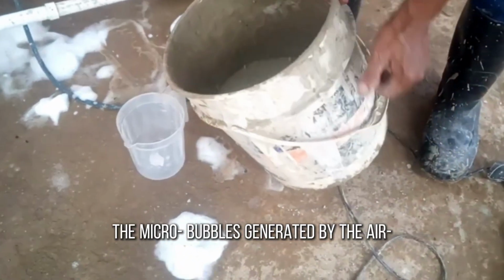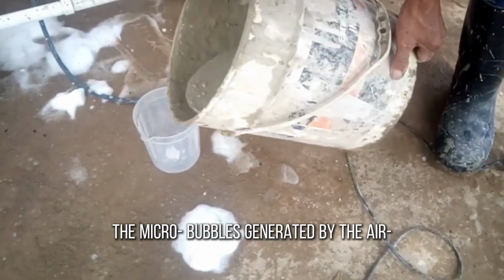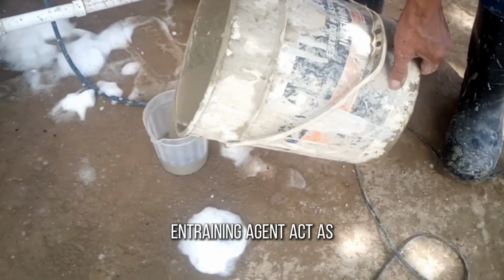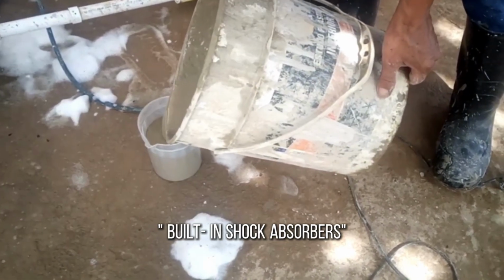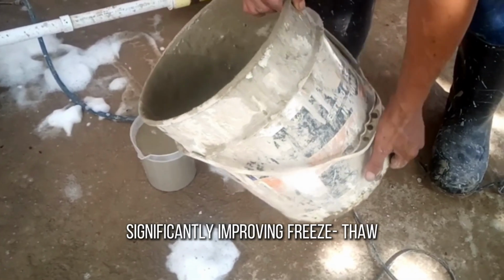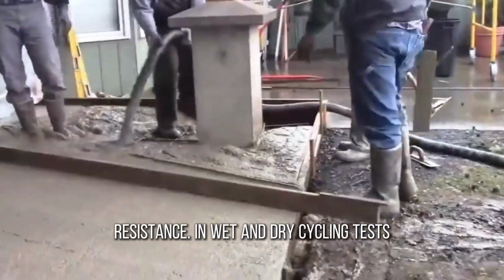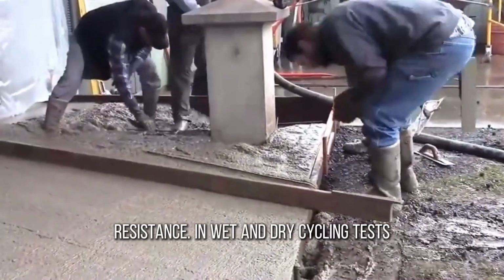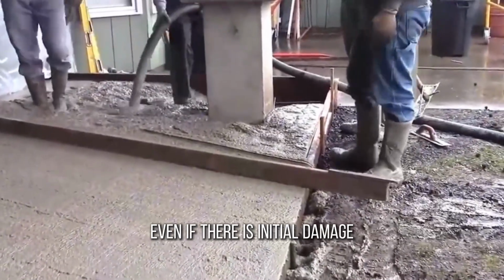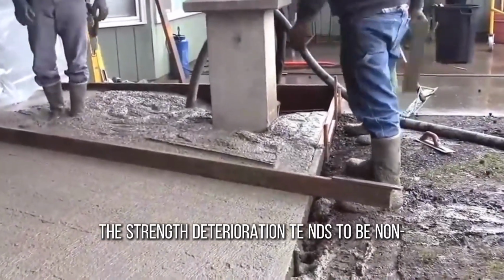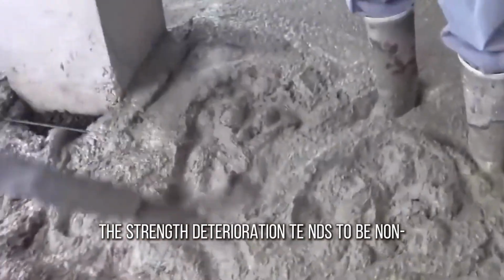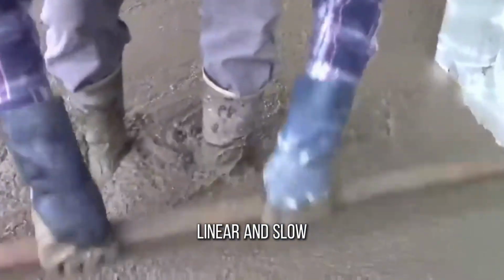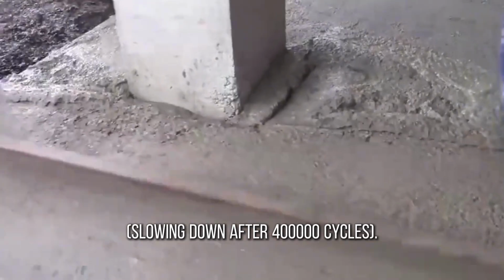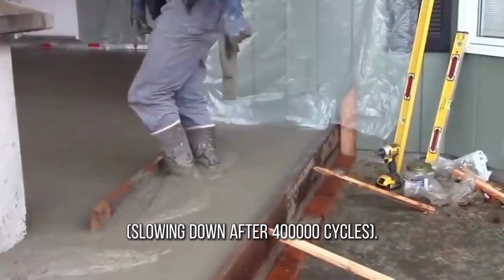The micro bubbles generated by the air entraining agent act as built-in shock absorbers, significantly improving freeze-thaw resistance in wet and dry cycling tests. Even if there is initial damage, the strength deterioration tends to be non-linear and slow, slowing down after 400,000 cycles.